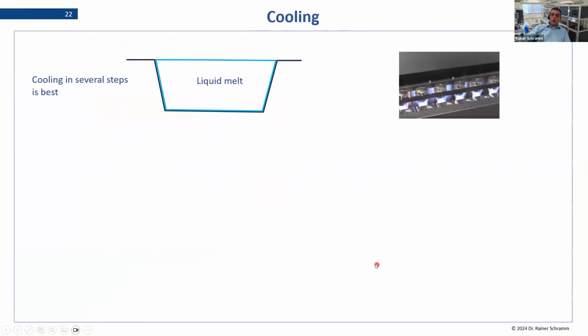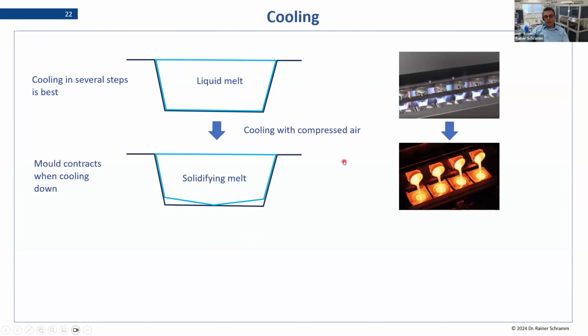Okay, let's talk about cooling. So cooling is also very important because in the end we want to get a bead, and this means it is a liquid which is becoming a glass. And this means that the crystallization is avoided. And this can only be done if you cool quickly down. And we normally cool with pressed air.